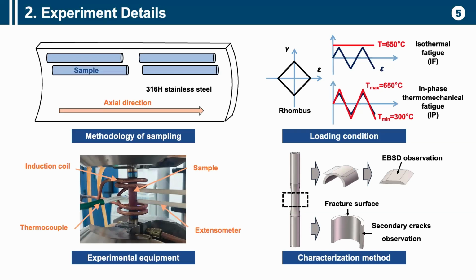The test is run on an MTS machine with induction coil heating for high temperature. Temperature is monitored with a K-type thermocouple, and strain is controlled with a tension-torsion extensometer. These are examples. After the test, we did SEM and EBSD observation of the specimen. We cut the specimen for fracture surface observation, for secondary crack observation, and for EBSD observation, on different surfaces and in different directions.